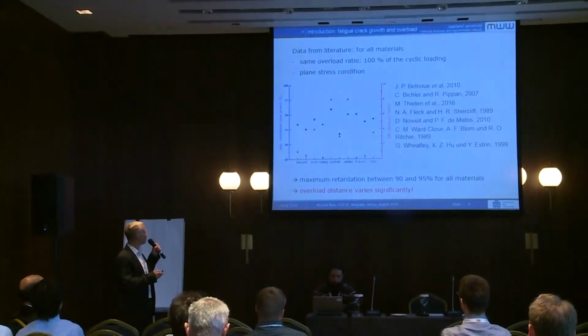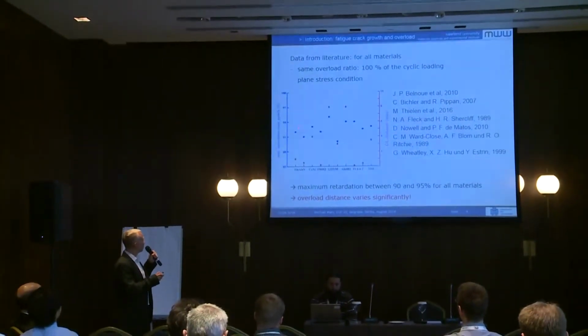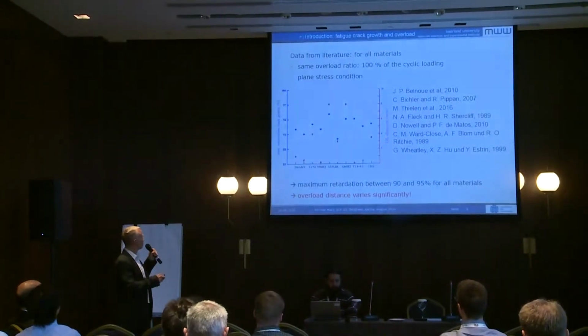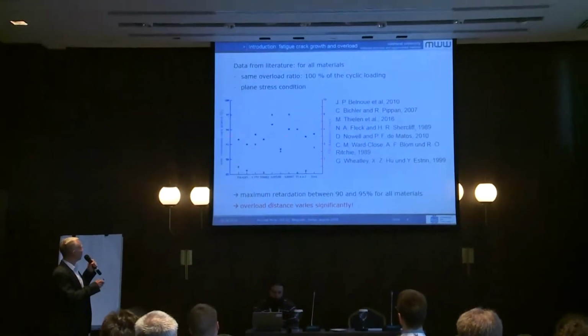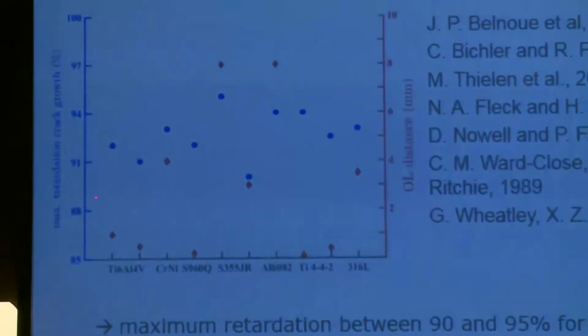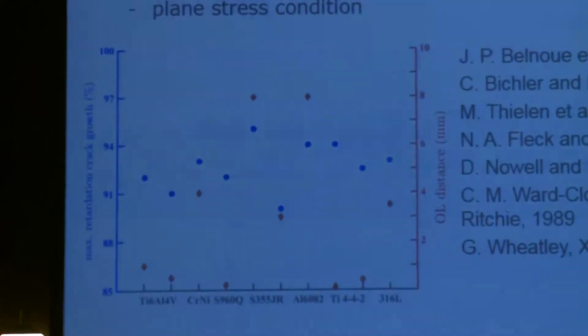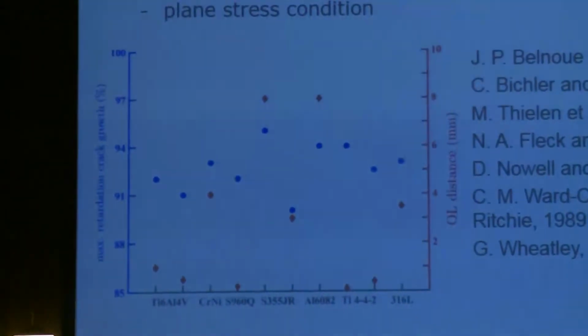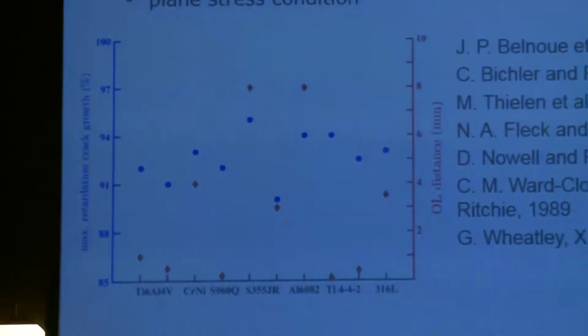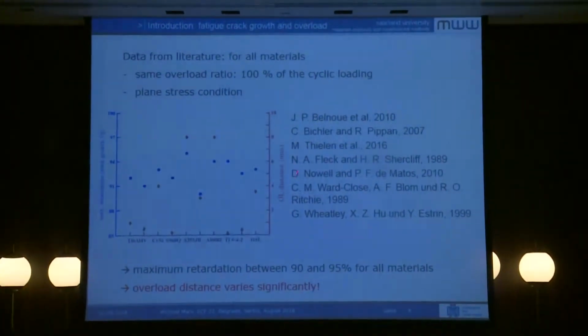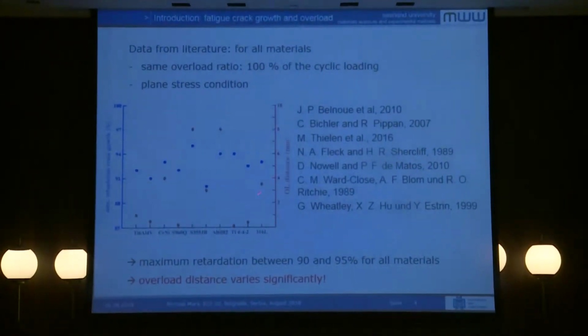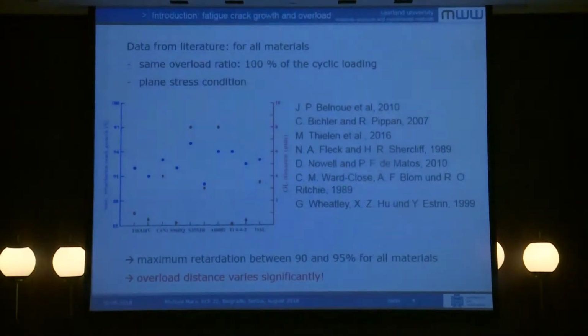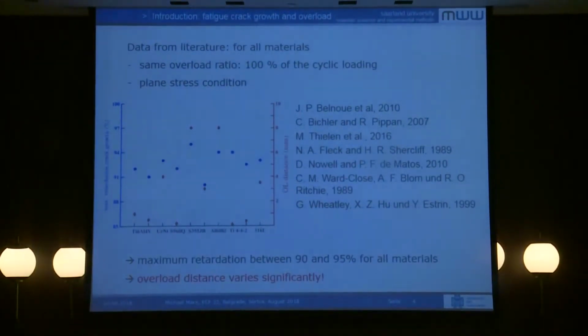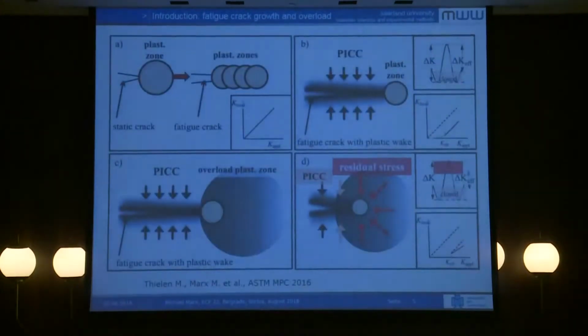If you have a look in the literature, we will find that the deceleration of the crack propagation rate for different materials, as you can see here, is always in the order between 90 and 95% of the prior crack propagation rate. However, the distance the crack grows through this area of influence is completely different, between several microns up to several millimeters in front of the crack tip, and therefore we investigated this a little bit more in detail. What are the mechanisms which are possible?